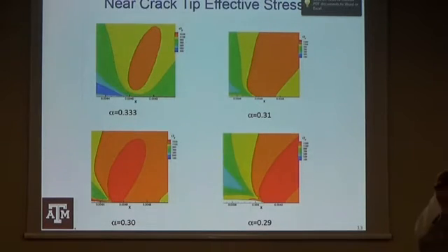By the way, I'm sure it's well known to at least most of you that, if you look at any ductile material, or actually almost any material, you look at the work of fracture, of actually making new free surface. It's a very small percentage of the total work that's dissipated in fracture. What really contributes to fracture toughness is the large-scale plasticity, large-scale dissipation. And what this is doing is increasing the large-scale dissipation. So anything that does that has an enormous effect on toughness.